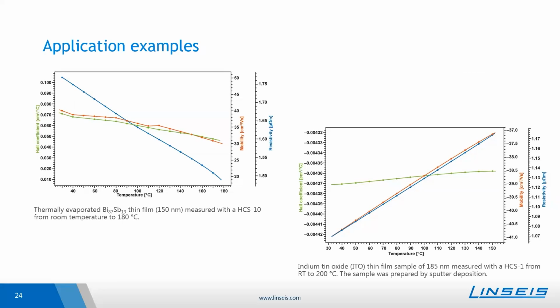On the left, you see a bismuth antimony thin film of about 150 nanometers, which was measured with an HCS-10 from room temperature to 180 degrees. So you can clearly see here the decreasing resistivity, mobility, and Hall coefficient. On the right side, you see indium tin oxide, shortly ITO. The thin film here was about